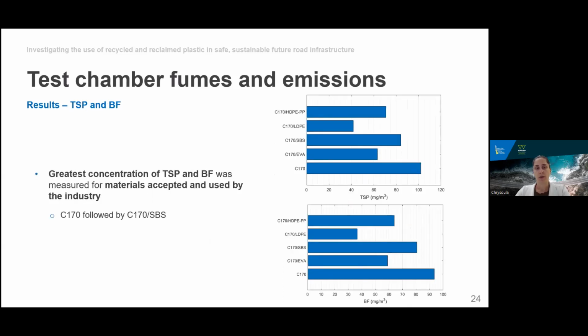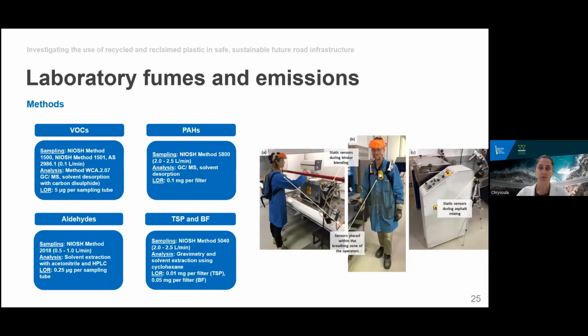C170 was also found to release the greatest concentration of total suspended particles and bitumen fumes, followed in both cases by the SBS modified binder. So overall, we can see that the emissions from recycled plastics modified C170 at temperatures as high as 180 degrees Celsius were comparable to those of commonly used materials when measured in an enclosed chamber.